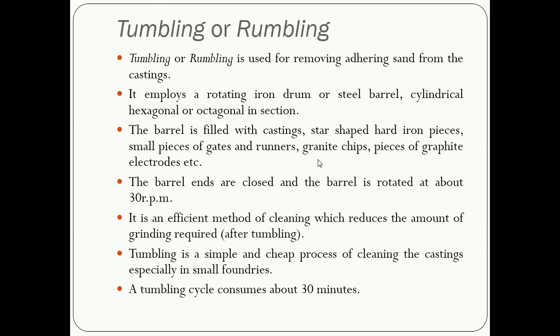Tumbling or rumbling method is used for removing adhering sand from the surface of casting. It uses a rotating iron drum or steel barrel, cylindrical, hexagonal or octagonal in section. This barrel is filled with castings to be cleaned, star shaped hard iron pieces, small pieces of gates and runners, granite chips, pieces of graphite electrodes. Everything is packed inside that iron drum.